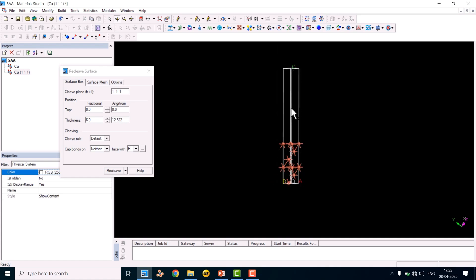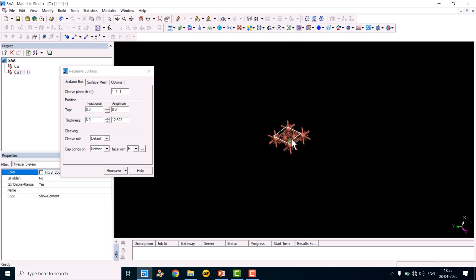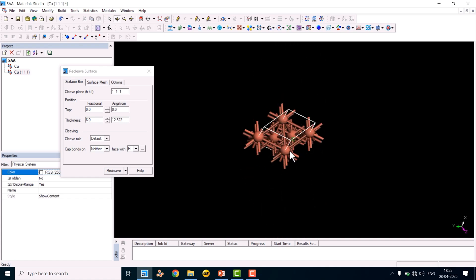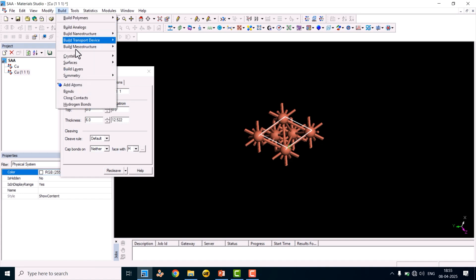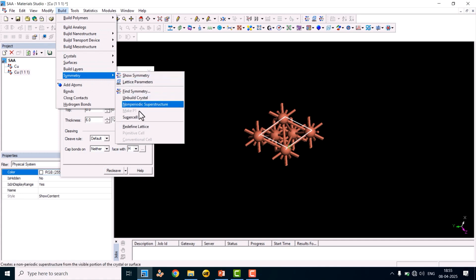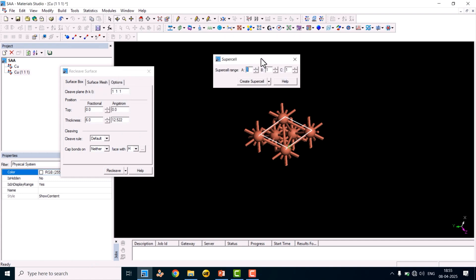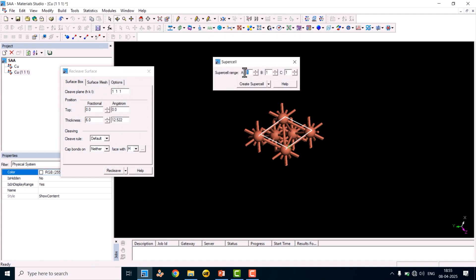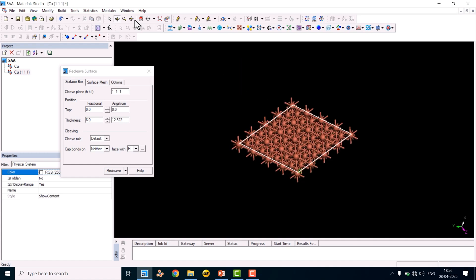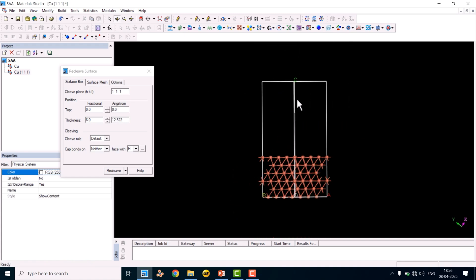The vacuum is now created. This is a one-by-one unit cell structure. We can make a two-by-two or four-by-four supercell as well. To create a supercell, go to Build, then Symmetry, and click Supercell. You will see fields for A, B, and C. We will make a four-by-four supercell — that way you can place your single atom alloy properly; otherwise the unit cell is too small. The four-by-four supercell of the copper 1,1,1 surface is now created.